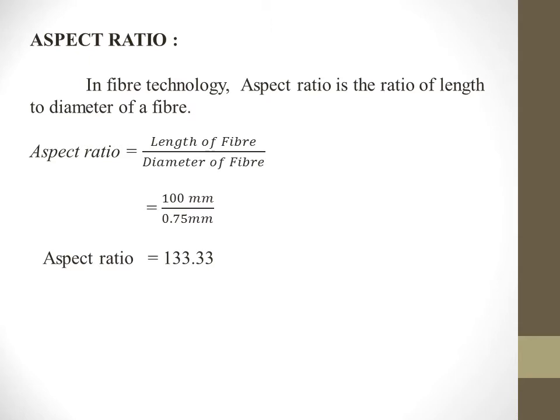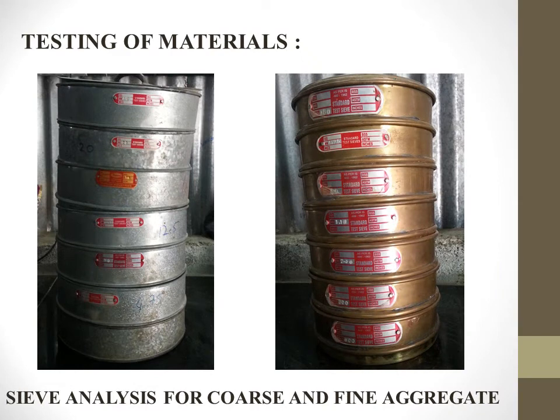length of those fibers was found to be around 100 mm, and the diameter of the fiber was found to be 0.75 mm. Thus the aspect ratio was 133.33. Then we had done the study on those materials. We had done sieve analysis for coarse and fine aggregate with the usage of these sieves which you are looking at, and also we had done specific gravity test on coarse aggregate and fine aggregate.